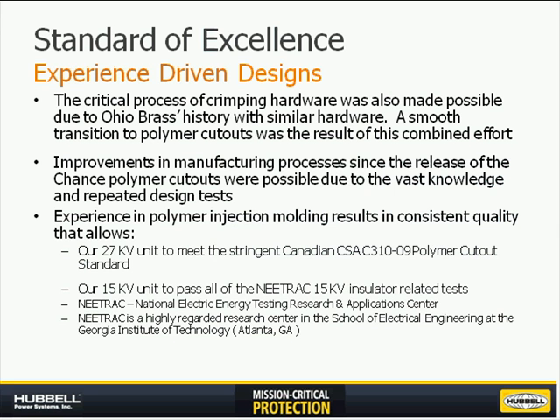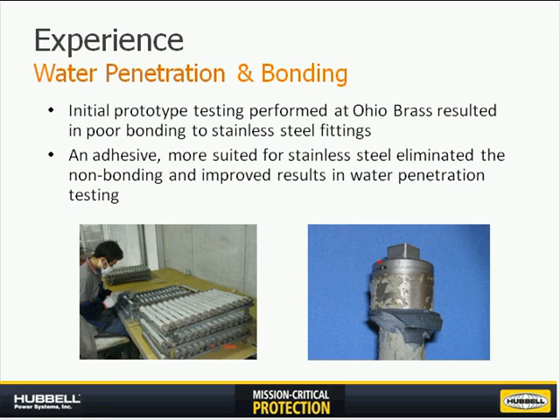Okay, one question we have is regarding the crimping process. A longitudinal crimp, as you'll see in the photo, we'll scroll back to it. You can see it in this photo. As you note in this region here, the crimp is a longitudinal crimp down the axis of the core rod. This aids in the stability of the fitting to the rod. A horizontal crimp can induce cracking, because the crimp is perpendicular to the axis of the fibers. So this can induce cracking by putting a point load on the fibers themselves.